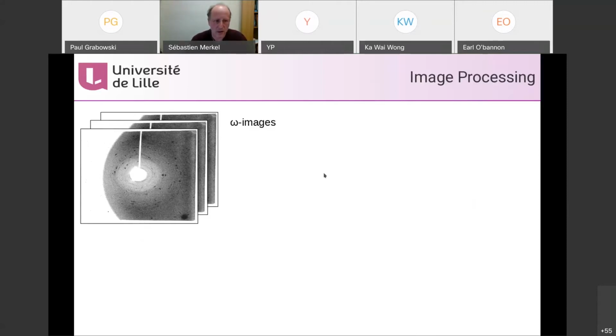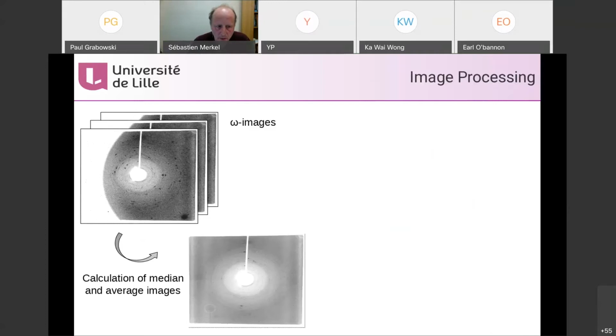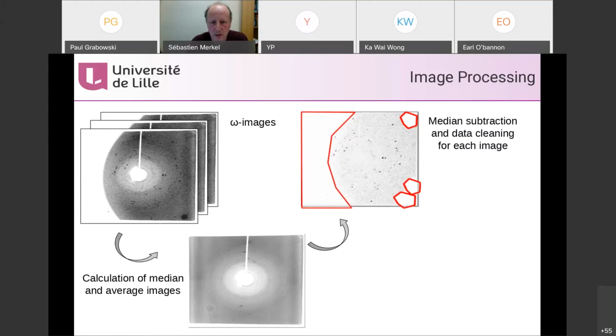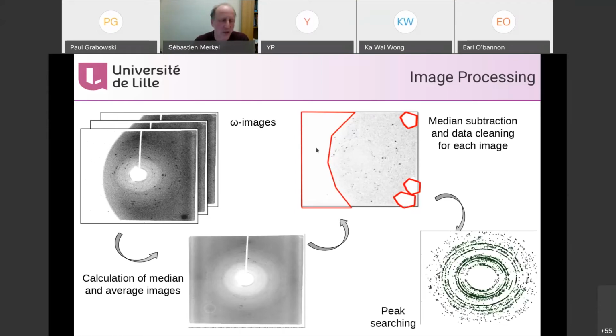To get to that type of information, you have these images you acquired at every step in the rotation. For each pixel on the detector, you can calculate the median value of the diffraction intensity that you measured. You get this median image, which has the effect of keeping the background, the powder, but the spots are removed from that image. If you subtract the median image from the diffraction image, then the spots show up very easily. You completely get rid of the diamond cell background, the diamond diffusion and the powder signal, and whatever is in the way is completely gone. You only keep the spots, the bigger grains in the sample. And then it's just a high pass filter to locate all the spots and those peaks.